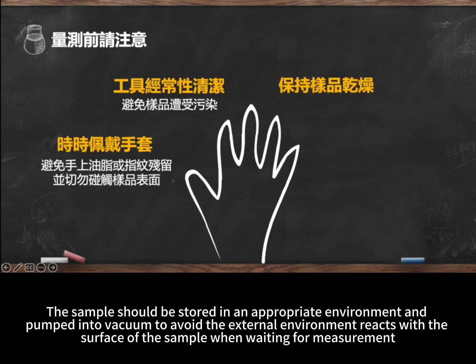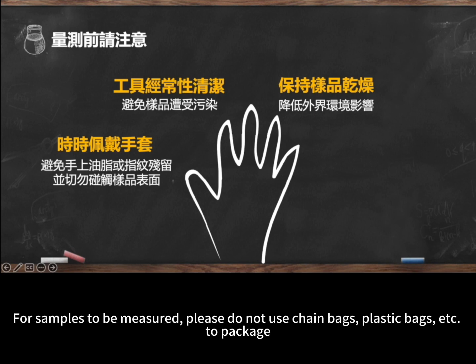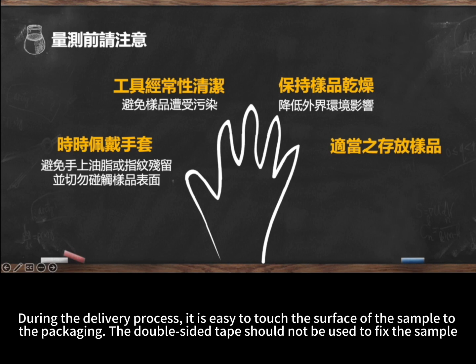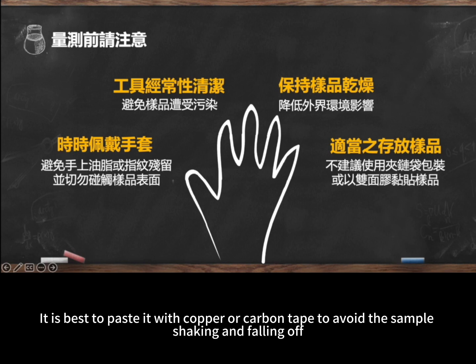The sample should be stored in an appropriate environment and pumped into vacuum to avoid the external environment reacting with the surface of the sample when waiting for measurement. For samples to be measured, please do not use chain bags, plastic bags, etc. to package. During the delivery process, it is easy to touch the surface of the sample to the packaging. The double-sided tape should not be used to fix the sample. It is best to paste it with copper or carbon tape to avoid the sample shaking and falling off.